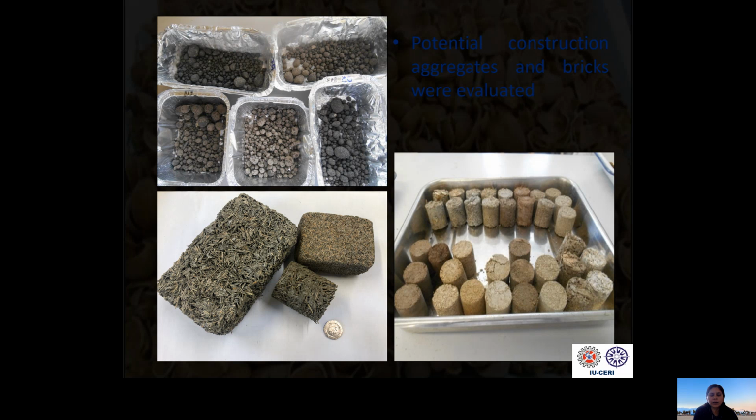And in this step, we found that not all biomass ashes were suitable, because you can see some of these monoliths are showing a bit of crack. Some biomass ashes were quite hygroscopic in nature and didn't perform very well. But I have to say most of the ashes were quite CO2 reactive, and they acted as a cement, or had a property to self-cement.